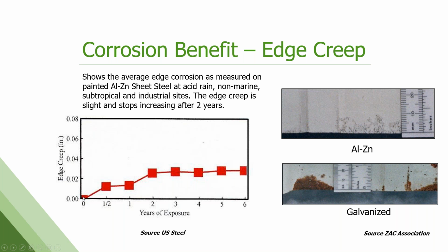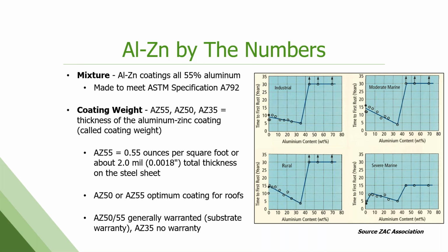And again, this graph kind of shows that plateauing that we see of corrosion on the aluminum zinc product. First few years, yeah, there's some corrosion happening, and then it just levels out. There are some ASTM standards that control this product that everyone's producing to. That would be A792. You'll see that in the specs, called out in architectural specs for 55% aluminum product. There's different coating weights, so we can put different amounts of this aluminum zinc on the strip. AZ55, AZ50 are going to be the most common for the building components world. We do see some AZ35 now, but usually for rainwater goods or interior products like appliances, we'll go down to that lower coating because they don't have the exposure to the elements.